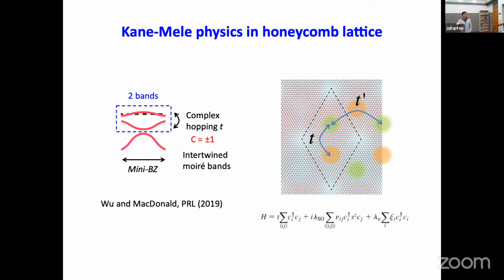It's also from MacDonald's group, 2019 in this case. If you happen to have two flat bands coming together, where the low energy physics cannot be captured by just one of the bands, instead you have to take into account the two bands. Things can become more interesting because you can bring the two bands close to each other. You can even introduce a band inversion between the two bands, and you can generate topological bands in that case, with a valley-dependent Chern number of ±1, for instance, with this two-band model here.